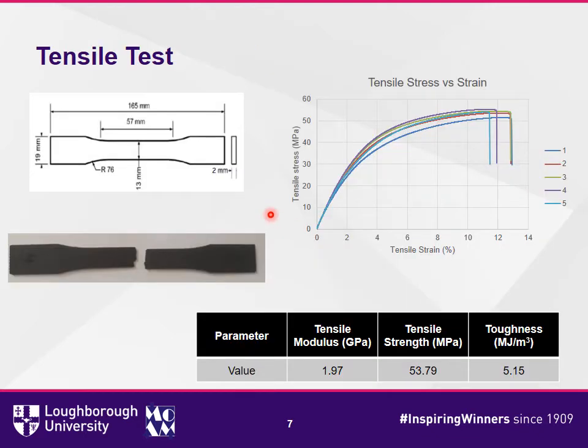For the mechanical characterization of the material, the tensile test was carried out as per ASTM D638 using a 2 mm thick specimen. The following tensile stress versus strain graph was obtained. From the graph, it was calculated that the tensile modulus is around 1.97 gigapascal and the tensile strength is 53.79 megapascal for the printed structure, and the area under the curve revealed a toughness of 5.15 megajoule per meter cube. After the test, observing the specimen showed a clean fracture, indicating a brittle failure.